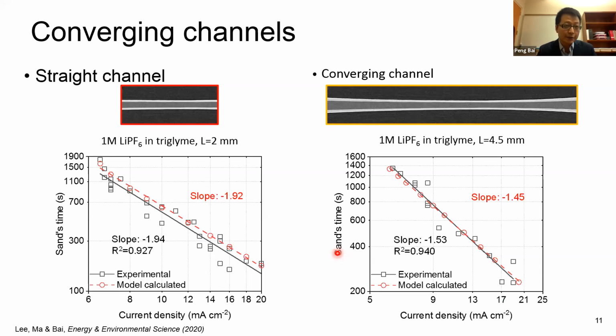So you can see here, for the straight channel, surprisingly, again, each dot on this log plot came from a single experiment using a different current density, where the voltage diverges, where you see the transition of metal growth. And surprisingly, you can see now for the relatively straight channel, we did get a slope very close to the ideal case. In contrast, if we leave the electrode in this tapering part, meaning that it will grow along a channel where the cross-sectional area is continuously reducing, a converging channel here, then as we obtained earlier, we got a slope of minus 1.45. Away from the ideal exponent, we have a positive deviation. So this confirmed that there is indeed a geometric effect.